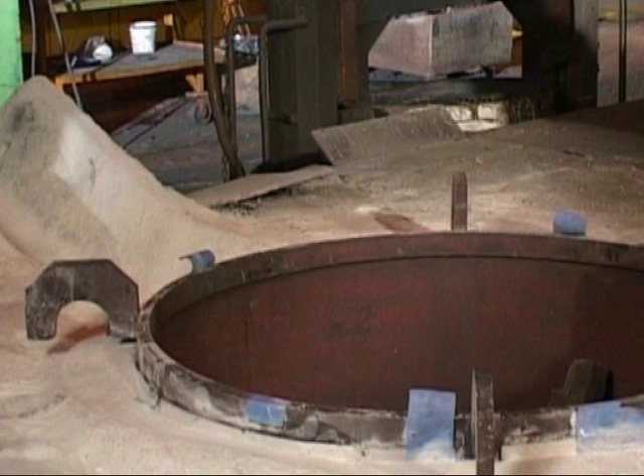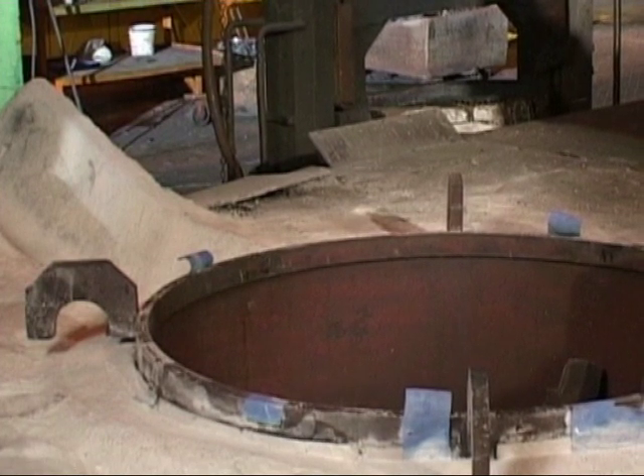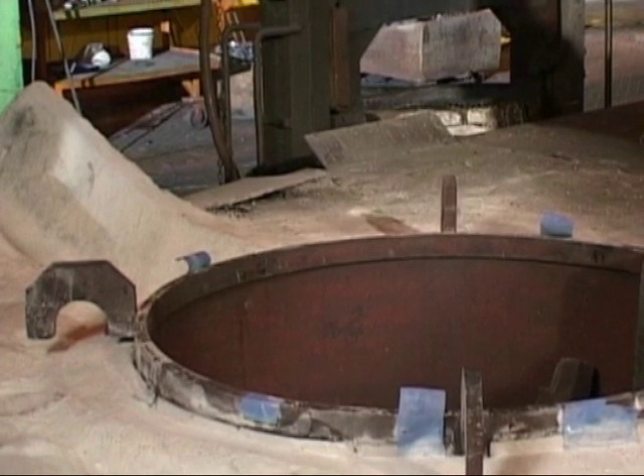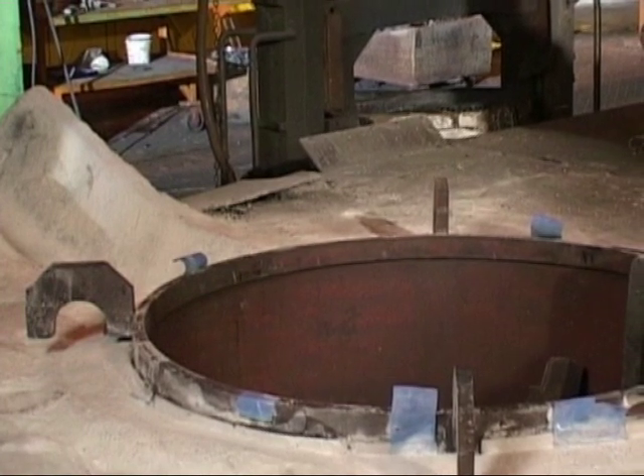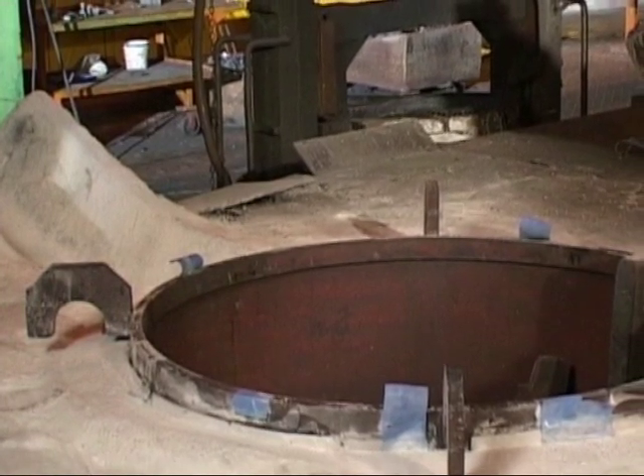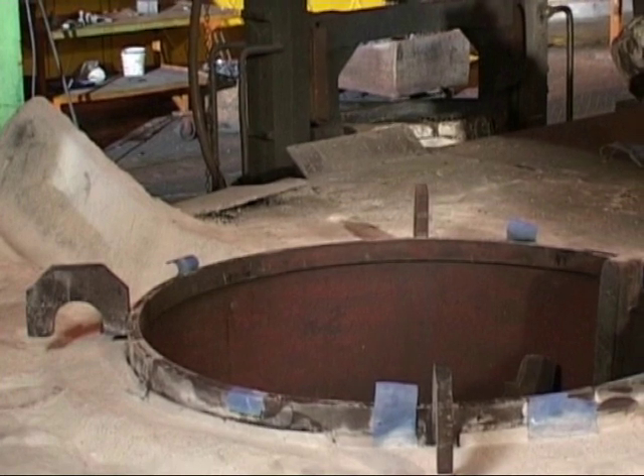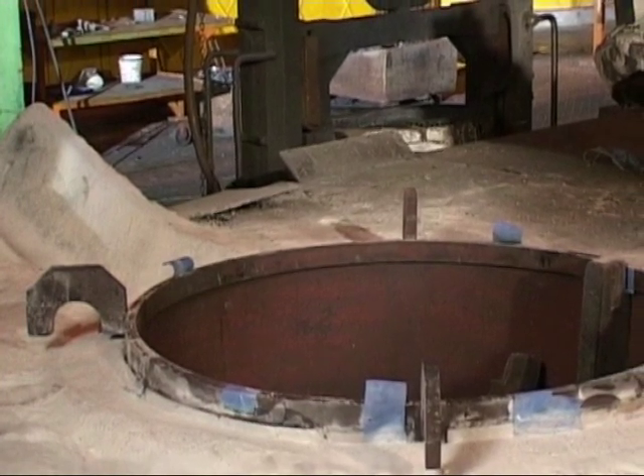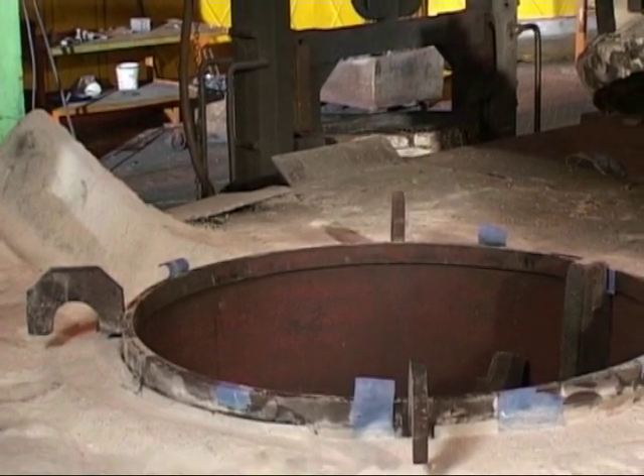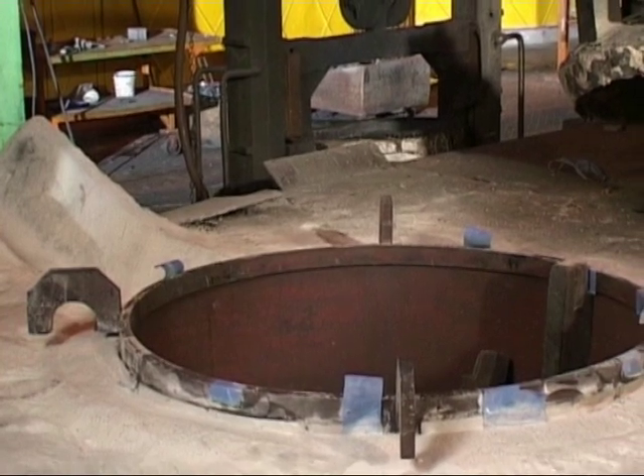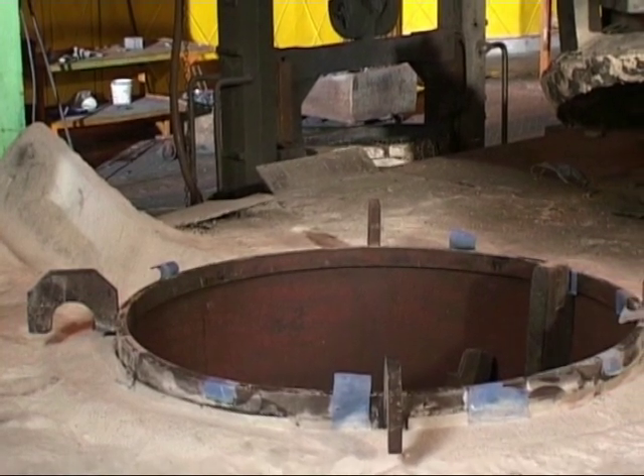The lining will show permanent linear expansion and rise above the level of the platform after some heats. If this interferes with closing of the furnace cover, do not ram quite to the top, but short of the top by about 30 to 40 millimeters.